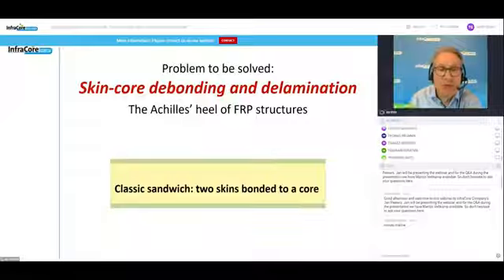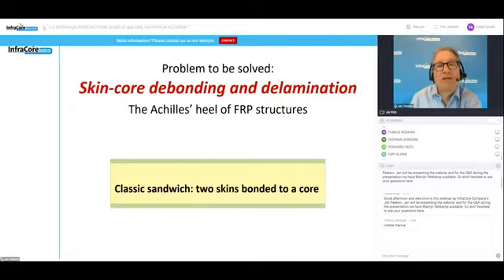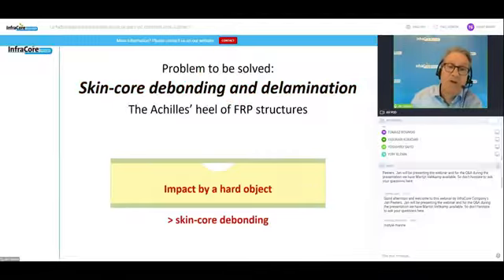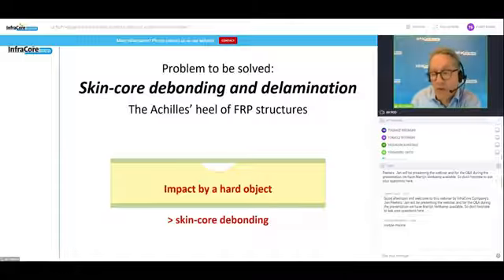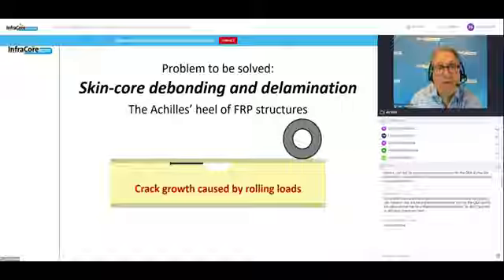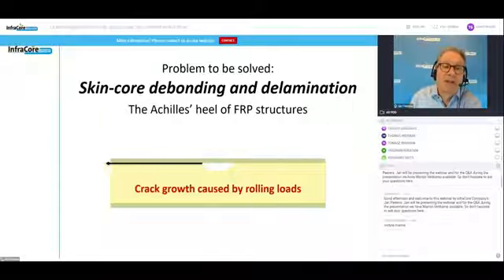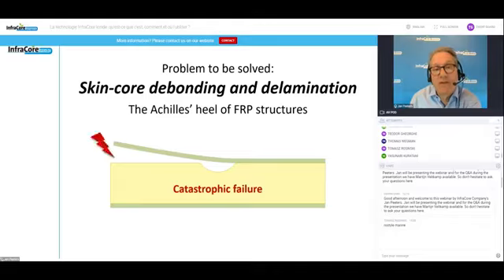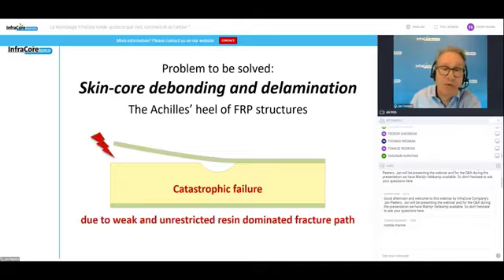I once designed my very first bridge as a classic sandwich structure, and I got a response from the Ministry of Transportation in Holland that it cannot be done. And there's a problem to be solved, and that is the skin core debonding problem and delamination. That's actually the Achilles heel of FRP structure. So if you have a sandwich structure, this is known, you drop a hard object on it, the core will crush, the skin is elastic, it will bounce back, and you get a skin core debonding. Very hard to prevent that. Normally that's not much of a problem, but when you start rolling wheels across a delamination like that, or debonding like that, you'll end up with a catastrophic failure in your bridge. So that's not acceptable as the backbone of an infrastructure product which should last for 100 years.